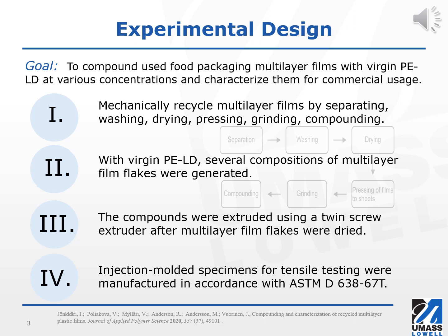So recycling multilayer films via mechanical processes such as separation, washing, drying, pressing, grinding, and compounding are the major works that were done in this work. Besides, several different compositions of multilayer film flakes were produced by using virgin LDPE as the precursor material. And after the multilayer film flakes had been dried, an extruder with twin screw was utilized in order to extrude the compounds, and the ASTM D 638-67T standard required injection molded specimens for tensile testing, and those specimens were made in compliance with the standard.